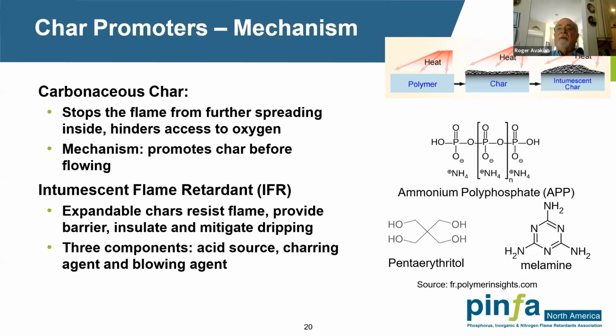And typically the three materials that are used to make an intumescent type of formulation are some sort of acid source, typically ammonium polyphosphate, but it can be other materials, some sort of source of hydroxy groups or carbon-forming material, in this case pentaerythritol, but typically dipentaerythritol and other materials, including carbohydrates, including lignins, as well as even starches can be used. But typically a melamine or a type of material that's going to form a gas so that you form this true intumescent char, which is basically a carbonaceous foam.